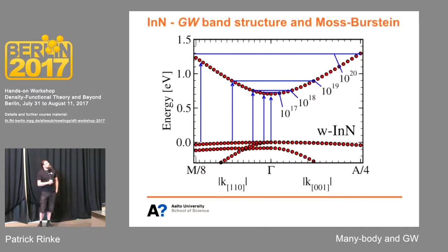Right? So this is then what we did, and here in red is the band structure. And you see the fundamental band gap in this GW calculation is 0.7 electron volts. So it is actually low, right? It is not 2 electron volts. So that was our statement, the band gap should be low. And then we went on to explain why such a variety of results was observed.